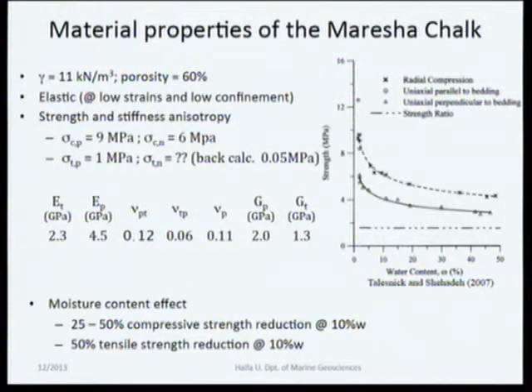So in tension, it's not more than 1 megapascal in the plane of symmetry, in the bedding plane. And actually we couldn't measure it exactly in the normal direction, but back calculations show that the tensile strength normal to the bedding planes is as low as 50 kilopascals, 0.05 megapascals. The elastic properties are given here. All of these, except for this one and this one, were measured. The other ones are calculated using theory of elasticity.